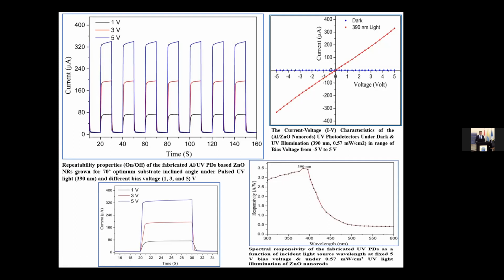It is dependent on the work function of the semiconductor, and we used aluminum. As we know, the work function of the aluminum is higher than the N-type zinc oxide, and we get the ohmic contact. Also, this figure shows the spectral responsivity of the fabricated UV photodetector as a function of the incident light source wavelength at a fixed 5 volt bias voltage under 390 nanometer wavelength of the UV light.